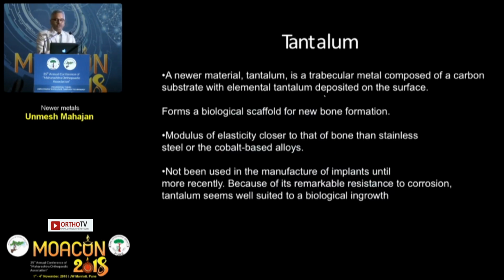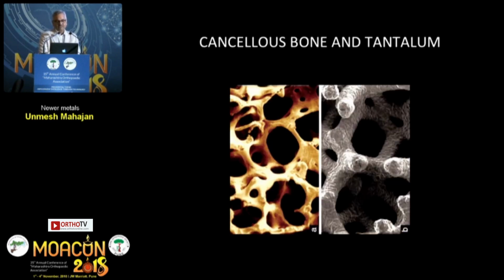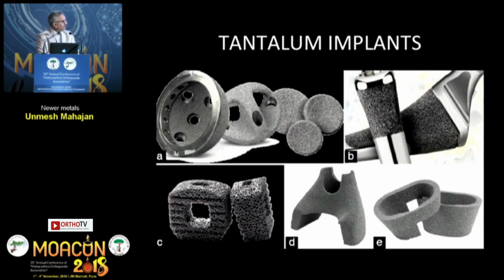Another metal that is used presently, not for actual implants as such, but is used within the orthopedic fraternity, is tantalum. It's a trabecular metal composed of carbon substrate with elemental tantalum deposited on the surface. It's a very good biological scaffold for new bone formation. Its modulus of elasticity is closer to bone and better than stainless steel and cobalt chrome. It's not been used as an implant but can be used as part of a construct. See, this is cancellous bone and this is tantalum, very close similarity to the cancellous bone, and this is used as a very good scaffold, especially in wedges and cones and everything. It is an upcoming thing. It is not used as a prosthesis itself but can be used as augments.